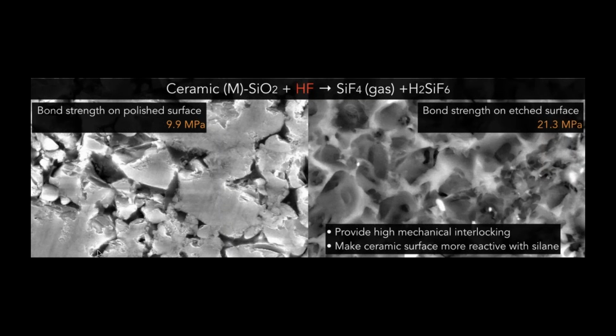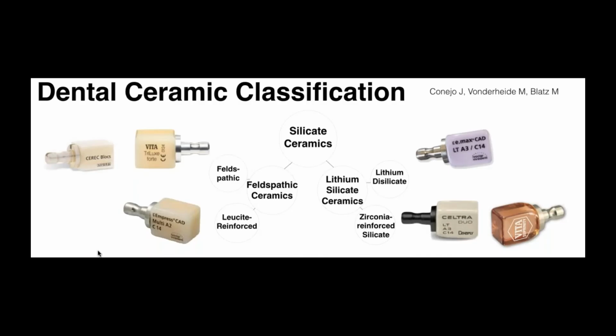This is an image on the left side immediately after milling. It's very flat. We never want to bond an Enamic restoration without the application of the hydrofluoric acid. And on the right side, you can see that we can obtain more than the double of the bond strength because we have this nice irregular surface where we have more surface area and there's better penetration of the silane, and those are the reasons that this can be bonded pretty well.